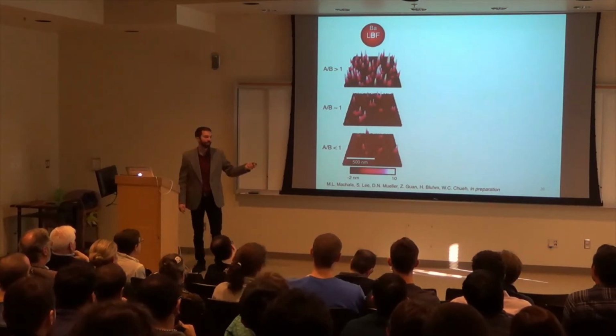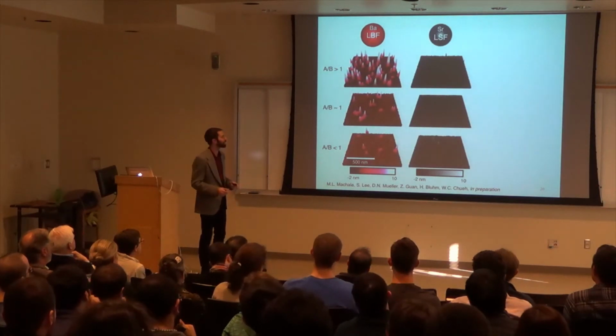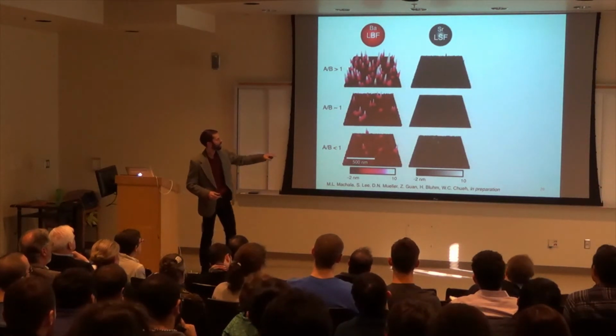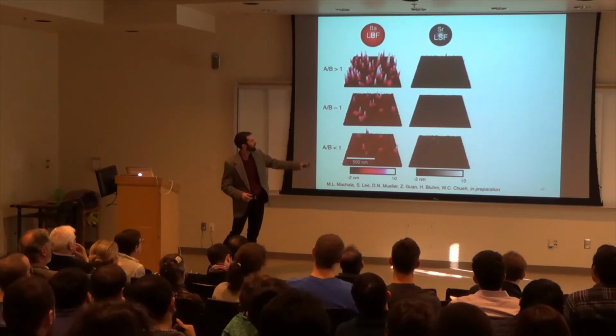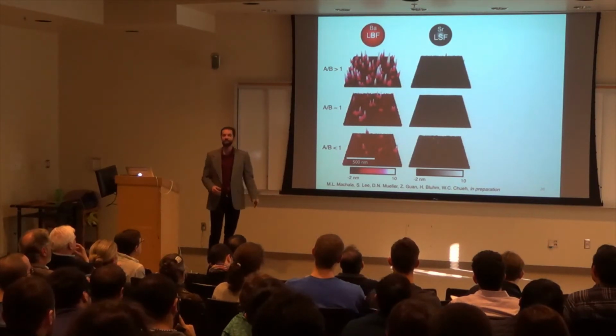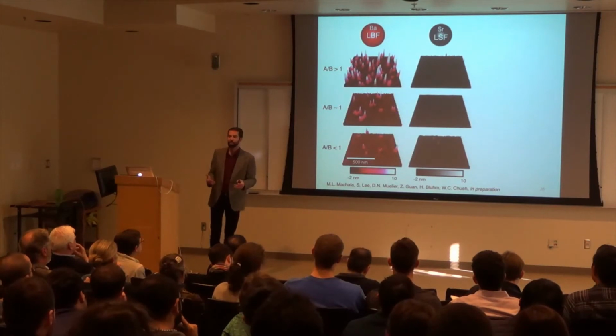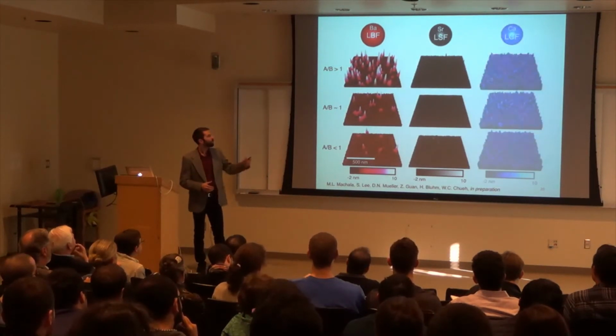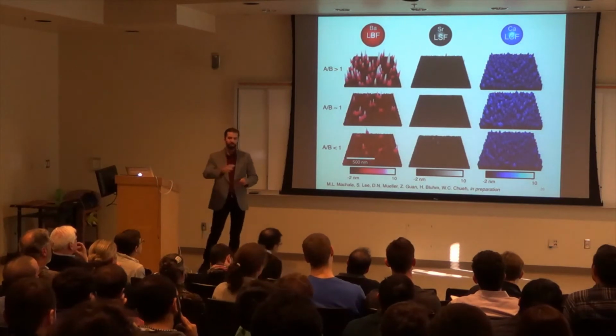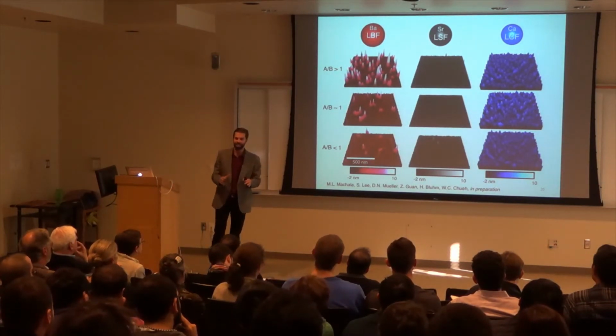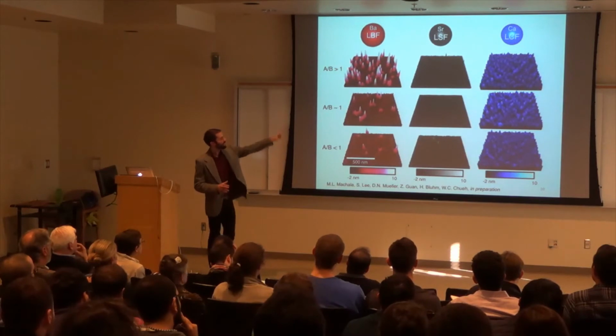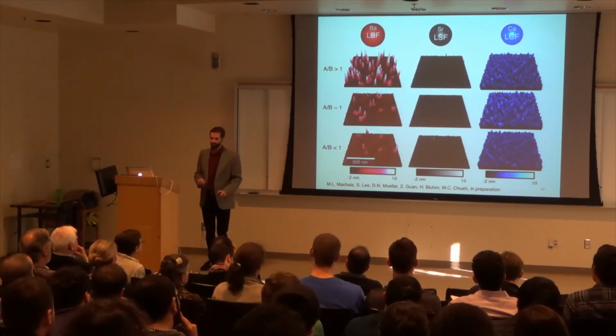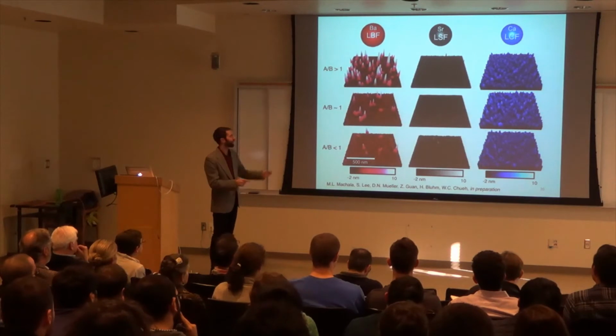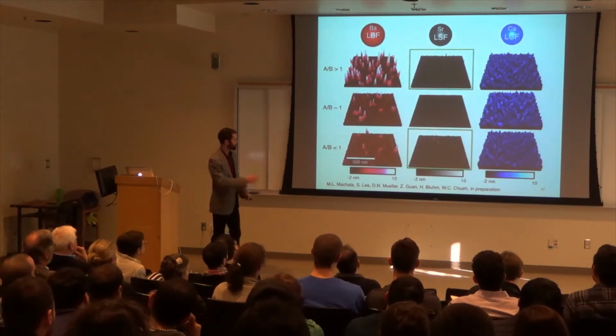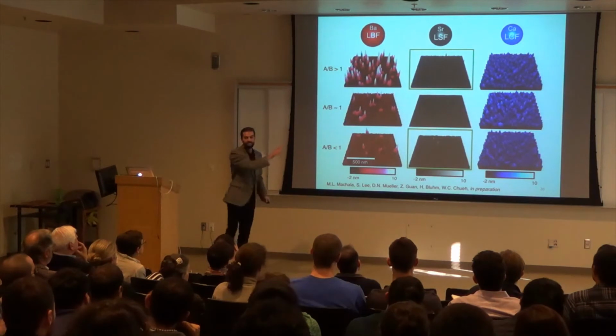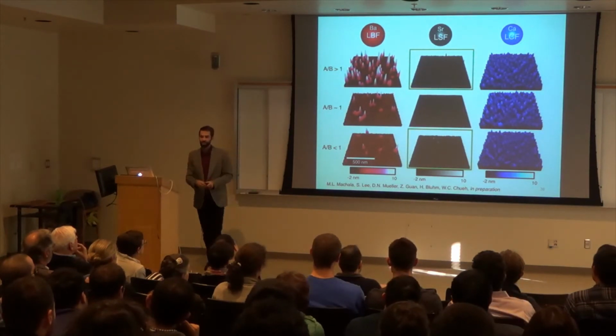We move on to strontium, which has a smaller ionic radius. We don't see quite as similar of a trend. We see a few precipitates forming, but we don't see anything as dramatic as the barium, and this might be due to the fact that the ionic mismatch is much smaller. When we move on to the calcium sample, however, it was kind of confusing because it has the most similar ionic radius to lanthanum, and we see this kind of rough surface morphology. I'm going to get back to that a little bit later, but first let's focus on the strontium series here, particularly A-site deficient and A-site excess. So more A-site or less A-site in there.